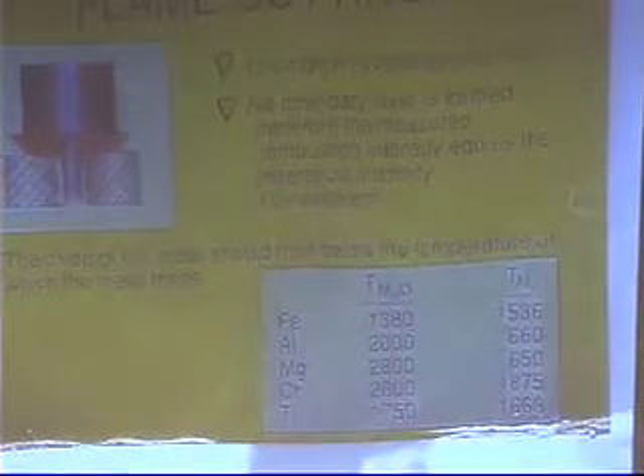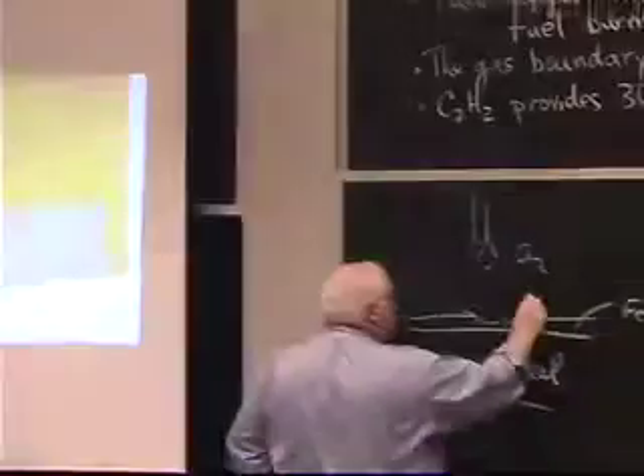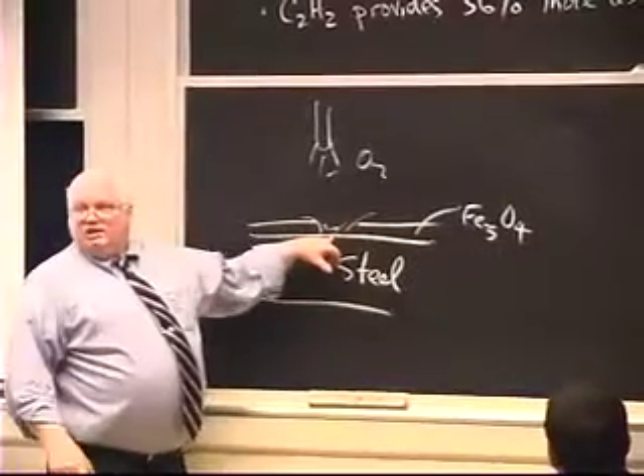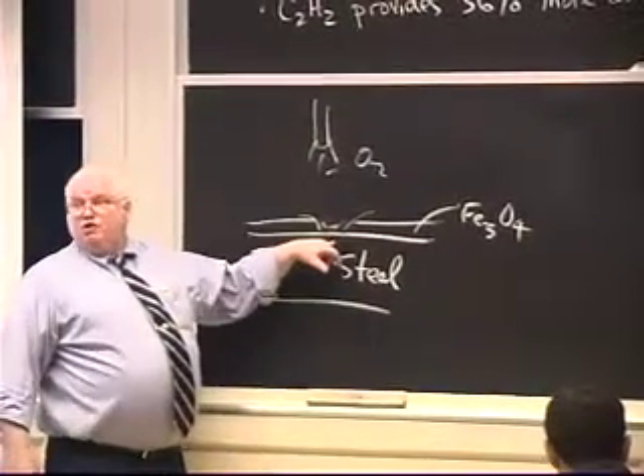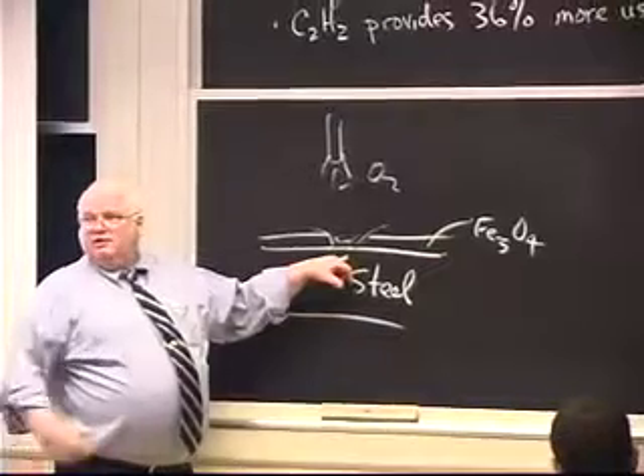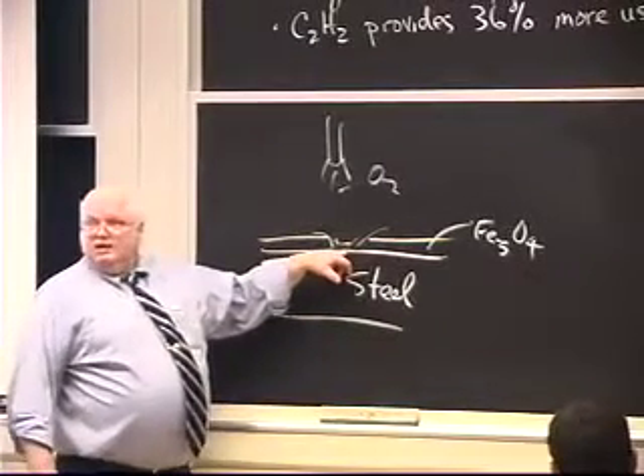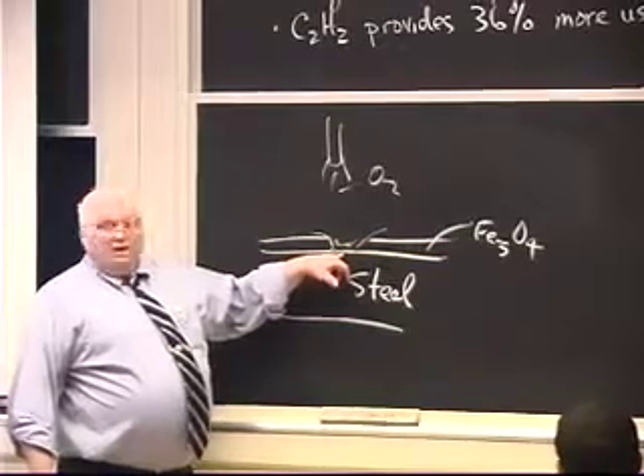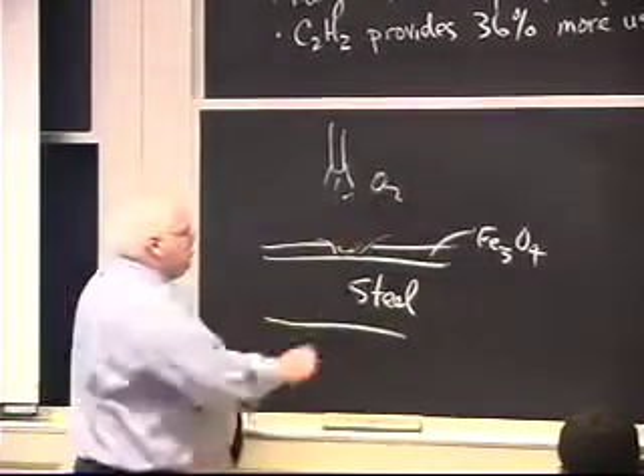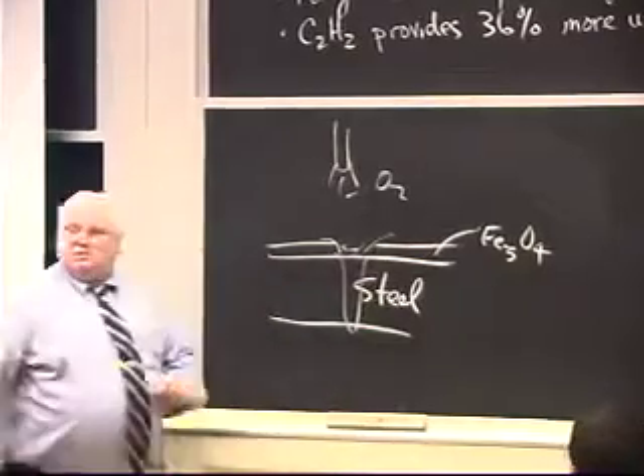For iron oxide, the melting point of the oxide is 1380 C, the melting point of the metal is 1536. So iron oxide actually melts below the melting point of iron. And so I actually can melt the surface of this. If I hit it with a pure oxygen jet, I can melt the surface, blow away the liquid iron oxide, and expose unoxidized steel to pure oxygen at 1500 degrees centigrade. Well, what's it going to do? It's going to oxidize. When it oxidizes, it gives off heat, and it will be molten iron oxide. So I blow away that iron oxide, and I just drill a hole through here in about 10 milliseconds.